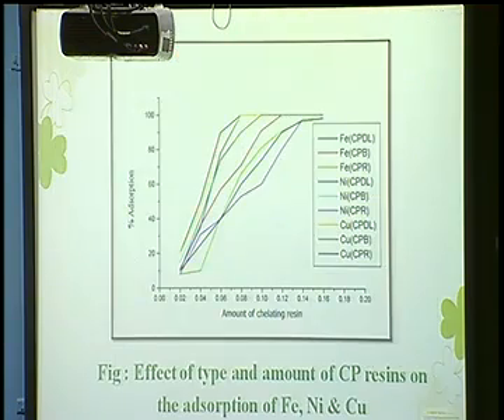As you can see in the table, the Calotropis procera dry latex is better as compared to modified bark and root. In the case of Calotropis procera dry latex, we are able to recover 100% metal ions with using 0.08 gram of the resin. This is the graphical representation of the data.